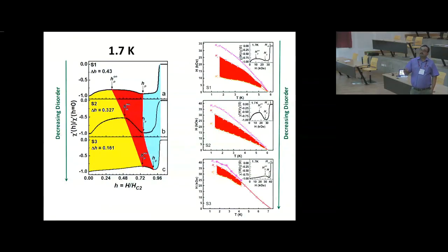This is where disclinations come in. And this red region is the hexatic state, hexatic or the orientational glass. As we go to samples that are cleaner, then we see this state actually shrinks, these two points come closer to each other, and one would speculate that for a completely clean system, possibly there would be just one transition, one first order transition.